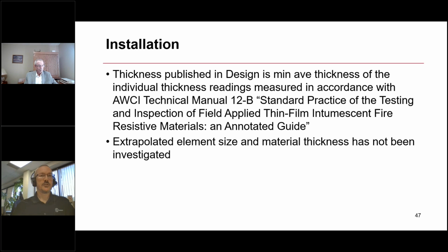No. So the BXUV guide says, for the thickness that's in those designs, the column design or the beam design, use the AWCI Technical Manual 12B, standard practice for the testing and inspection of field applied thin film intumescent fire resistant materials. In there, there's a method, I think it's based on the total square area at the job site, for how many readings to take. So that's what the guide information says about the thickness that's published in the design. Use the AWCI manual for how many readings to take at the actual job site to ensure that the right thickness of intumescent material is on the column or beam.